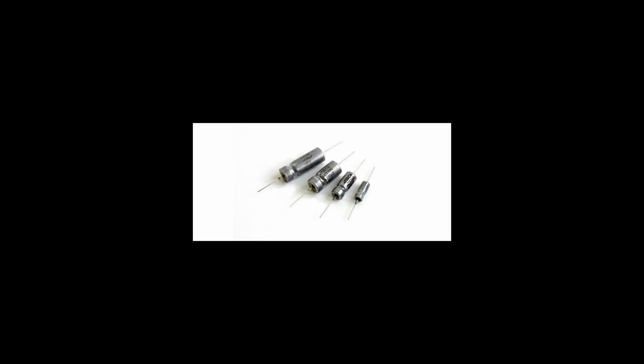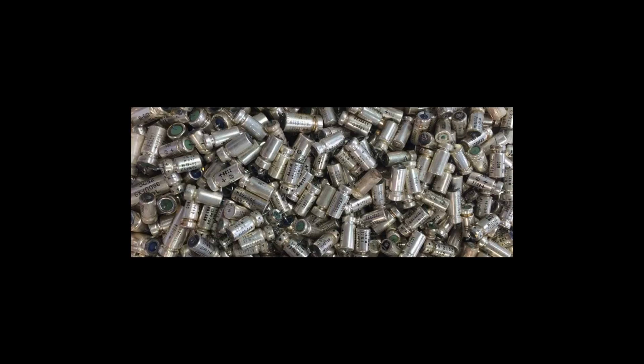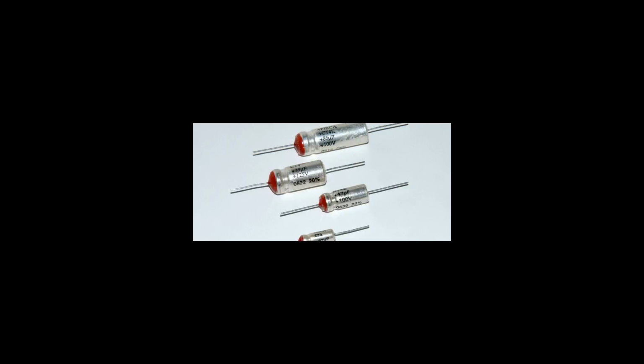Although the fundamental inventions came from the Bell Labs, the innovations for manufacturing commercially viable tantalum electrolytic capacitors were done by the researchers of the Sprague Electric Company. Preston Robinson, Sprague's director of research, is considered to be the actual inventor of tantalum capacitors in 1954. His invention was supported by R. J. Millard, who introduced the reform step in 1955, a significant improvement in which the dielectric of the capacitor was repaired after each dip and convert cycle of manganese dioxide deposition. This dramatically reduced the leakage current of the finished capacitors. This first solid electrolyte manganese dioxide had 10 times better conductivity than all other types of non-solid electrolyte capacitors. In the style of tantalum pearls, they found very quick broad use in radio and new television devices.